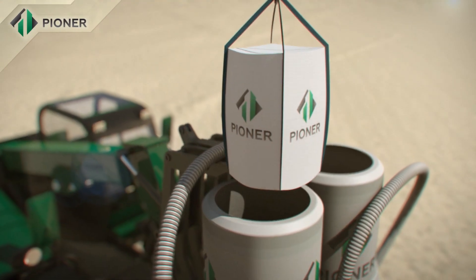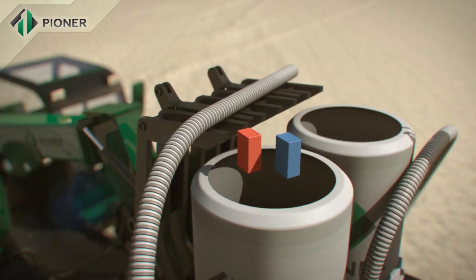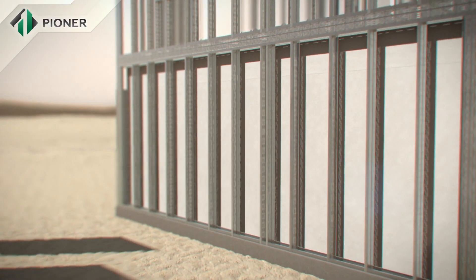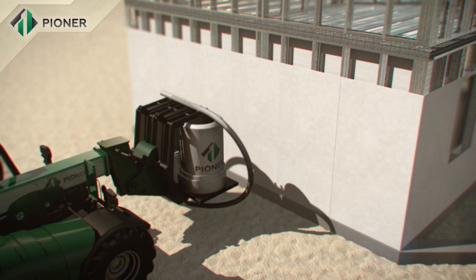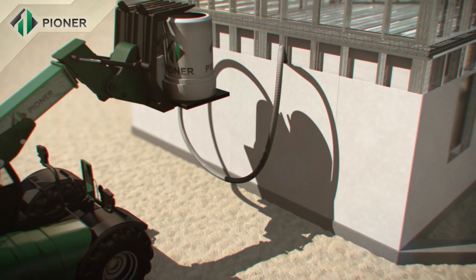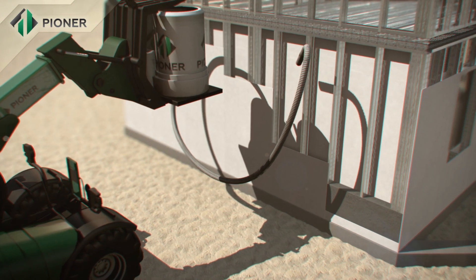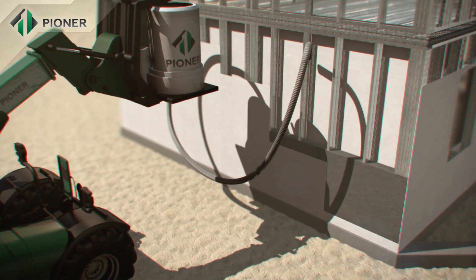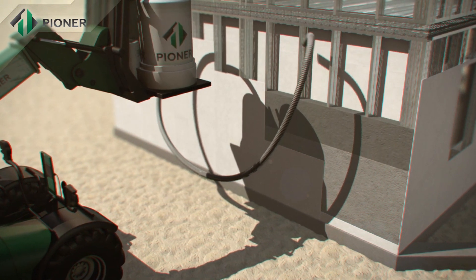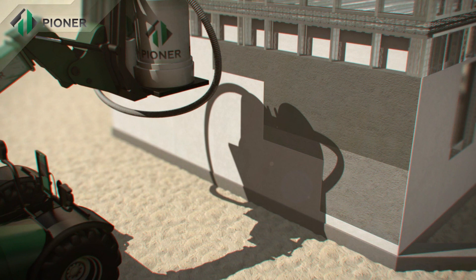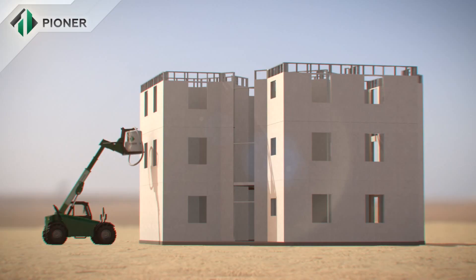Dry mixture of Pioneer compound is mixed with water in a special hydraulic mixer that does not require connection to an electric supply, then poured between the installed panels, completely filling the space inside. Within 40 minutes, the mix increases in volume two to three-fold and turns into a homogeneous monolithic structure. An important advantage of Pioneer technology is that it allows for construction of buildings in all regions, including those remote from power supply.